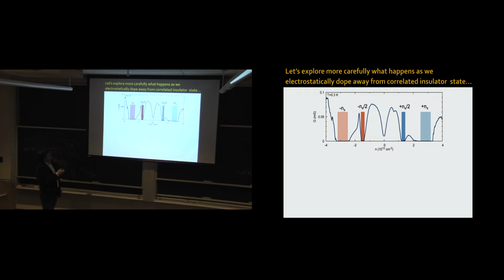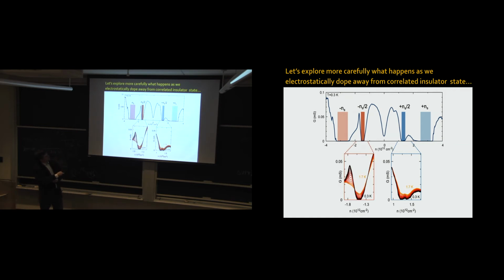So when we were measuring these devices in two-terminal, remember, from here to the right, we're adding electrons. We call this the correlated insulator state for electrons. From here to the left, we're adding holes. We call this the correlated insulator state for holes. When we look at the temperature dependence of these devices, around the correlated electrons not much happens. The system is an insulator. When I cool down, it conducts less. That's what insulators do. That's what we expected. But then when we looked around the correlated holes, for the insulator state itself, it was the same thing. Colder, conducts less. But right next to it, this thing seems to conduct more the more we cool it down. So we saw that conductance enhancement, and we were like, that's kind of strange. Let's see how well this thing really wants to conduct.